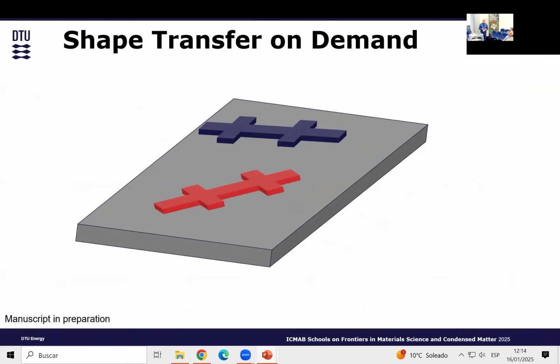Then I'm coming to the shape transfer on demand. And the question that we ask here is, okay, we can make a material, we can make a freestanding membrane, and we can transfer it to any substrate, which is okay. And if we want to make a device, we take it to the clean room, whatever clean room you have, and you do lithography, and then you end up with something. This is a Hall bar, for example. So this is one way of doing it.